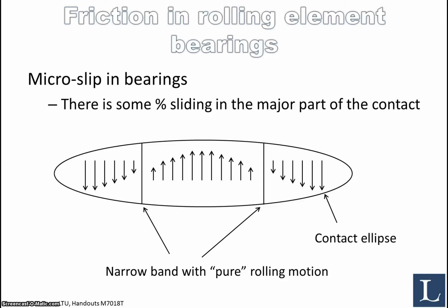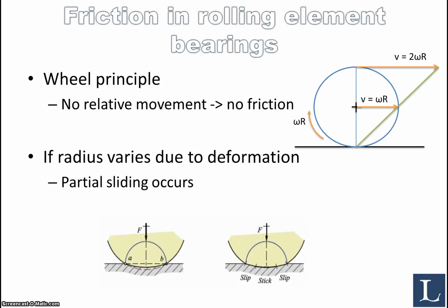And as you can see, in some part of the contact, the ball will actually have a reverse velocity, and in other parts of the contact it will have a forward velocity, and there will be some narrow bands where you will have pure rolling. Now this will give rise to a certain amount of slip, which is what is known as rolling friction. It can be exemplified by the wheel principle. For instance, in the figure, if you have no relative movement, you will also have no friction. But as soon as you have, for instance, a varying radius in the contact, you will encounter some slip. And if the radius varies due to deformation, you may encounter partial sliding, which consumes a part of the energy and is the rolling friction that occurs.